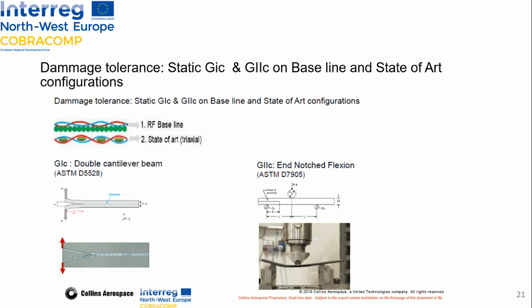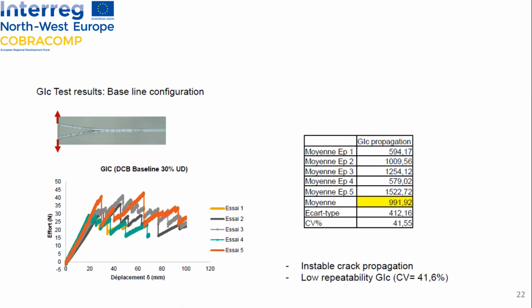Now, a few words about damage tolerance. With the static G1C and G2C tests, the G1C with a double cantilever beam and the G2C with the end notch flexion, what we can see with the graph here is that we can show some unstable crack propagation, and the composites reach a value of 992 J/m², but with a high dispersion in the results, as we can see with the high value of the coefficient of variation.